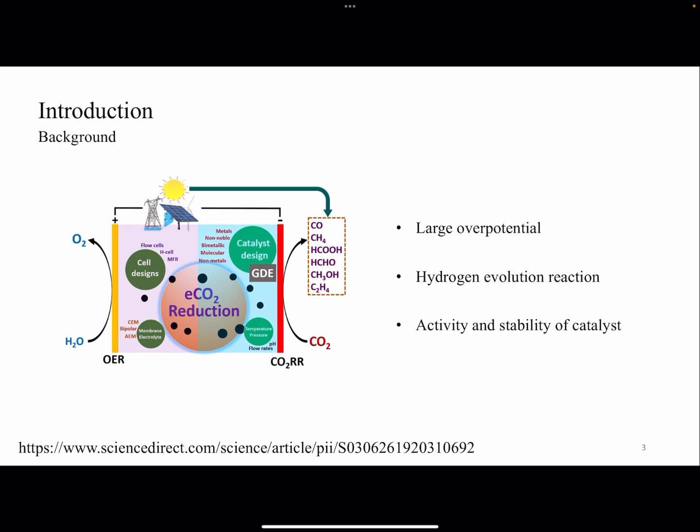However, there are two major problems in CO2RR. The first one is high overpotential, because activating CO2 to form a radical anion requires a huge amount of energy. And the second one is the hydrogen evolution reaction, which is a competitive reaction.